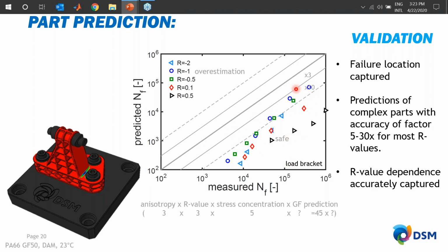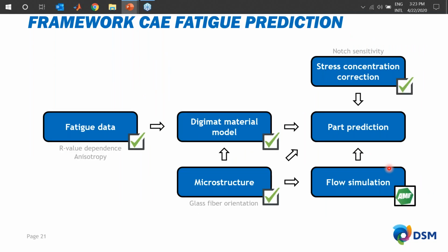So although we wanted to do a bit better, we were already quite satisfied with this result after analyzing it properly. So in conclusion, we can capture the failure location, and we are slightly conservative, but we can already predict within a factor 5 to 30, and we can properly capture the R value. So I hope that it also gave you a glance at the part prediction capabilities.